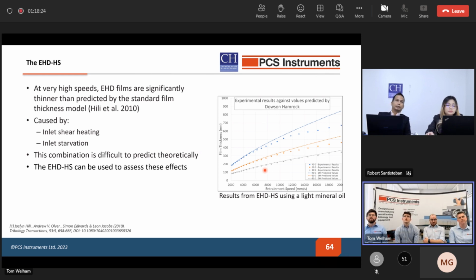So I wanted to cover why we think it's important to test at high speeds. So here's shown some work from researchers at Imperial College. And this plot on the right, which was taken using the EHD HS, shows that the measured EHD films are actually significantly thinner than the standard model for film thickness predicts. And it was shown in this work that this behavior was caused by a combination of inlet shear heating, which reduces viscosity, and inlet starvation, which I showed earlier can greatly reduce film thickness.